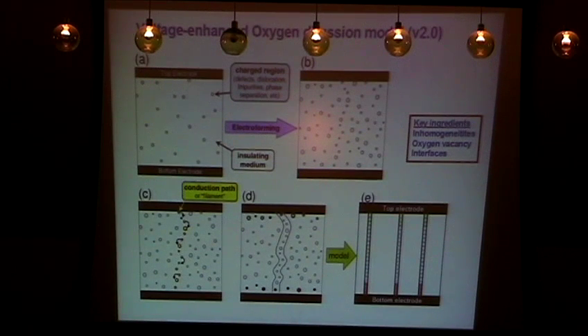Okay, so we go back to what this dielectric is and what goes on in this system when you produce a resistive switching. Many of these systems need to be formed. When electroforming, we think that this promotes the existence of these oxygen vacancies and/or defects, and that these things get organized in some fashion through the effect of electroforming. Eventually, you're going to get a lot of these defects and vacancies organized in conductive paths.